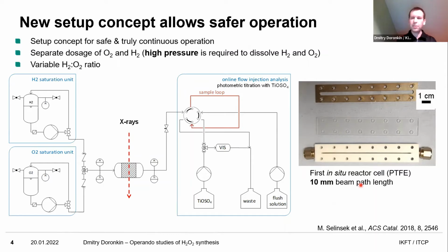As X-ray windows, we're talking about palladium catalysts, so quite high energies. And therefore we took polycarbonate. I mean, it's not something you read in the textbooks when you read about windows for X-ray absorption spectroscopy, but it works in our case for 24 keV, so why not? And we get an advantage that we see what happens with our catalyst bed.